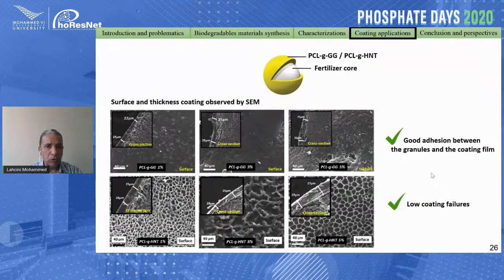So we coated the granules only by dip coating in THF. Unfortunately, one drawback of our nanocomposite is that the polymer is soluble in THF. By dip coating, as you can see, we have really thin films, and we have good adhesion, even with halloysite nanotubes or with guar gum, between the granule and the coating film. This is a good thing for us.